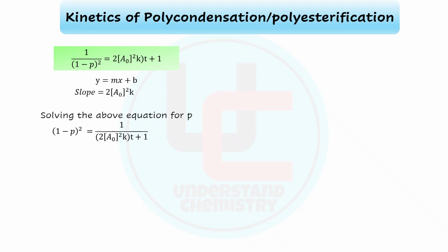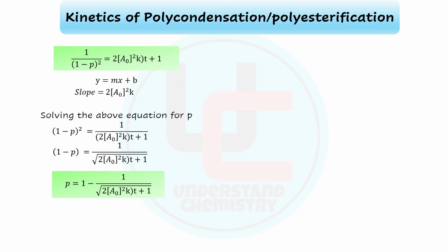Solving this equation for P, we end up with this expression. From this equation, we can say that at time t equal to 0, P will be equal to 0, meaning there is no reaction, and after infinite time, P is equal to 1. This indicates a complete conversion.